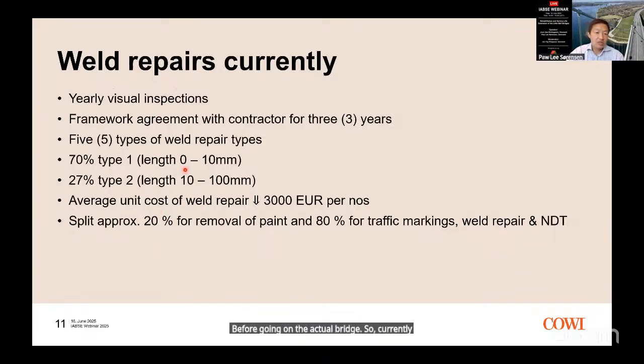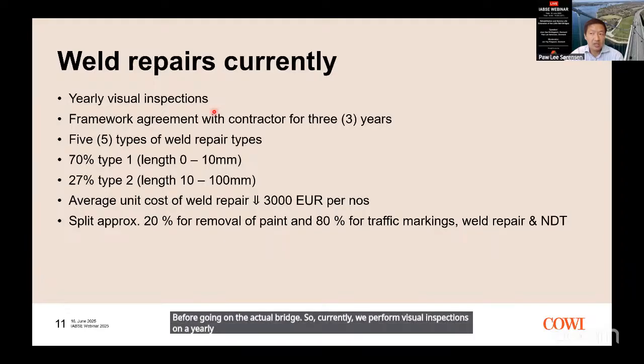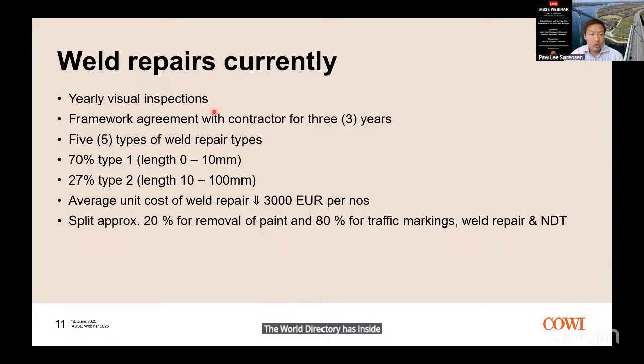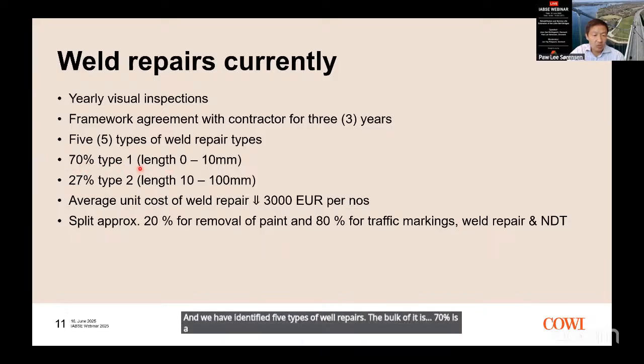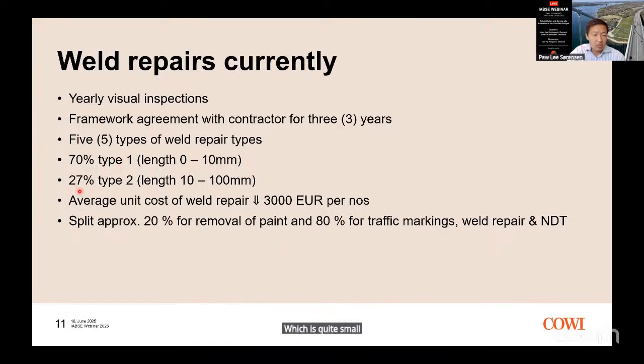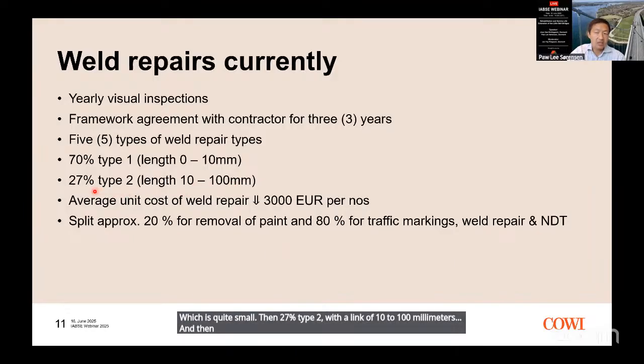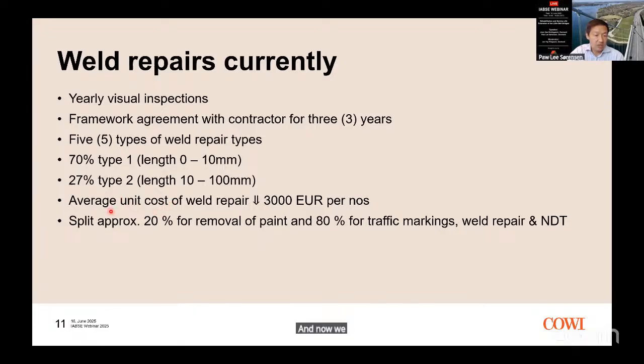So currently, we perform visual inspections on a yearly basis. The Road Directorate has entered a framework agreement with a contractor for 3 years, and we have identified 5 types of weld repairs. The bulk of it, 70%, is one called type 1, which is quite small. Then 27% type 2 with a length of 10 to 100 millimeters. And then the remaining are types 3 to 5. But the bulk of it is quite small welds. And now we have an average unit cost that is down to 3,000 euros per repair. And also the split has been slightly changed.